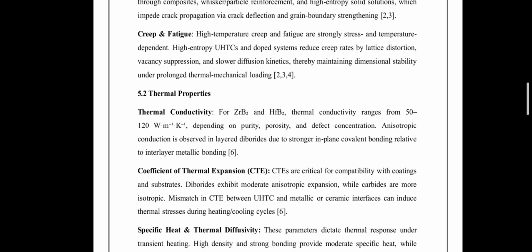Next, the coefficient of thermal expansion is a critical parameter for coating compatibility and structural integrity. Carbides are generally more isotropic. Diborides show moderate anisotropy, and CTE mismatch between ultra high temperature ceramics and substrates or coatings can generate severe thermal stress during heating and cooling cycles. The specific heat and thermal diffusivity govern the transient thermal response, while the strong bonding yields moderate heat capacities and defect induced phonon scattering reduces diffusivity, directly impacting thermal protection system performance.